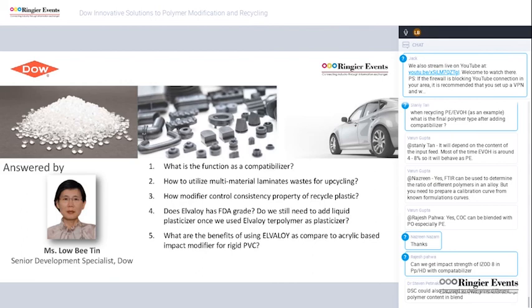The third one is that Elvaloy also acts as a processing aid. We have seen that it enables you to reduce the processing temperature by up to 20 degrees, so you can process at 160. With this lower extrusion temperature, it allows you to reduce the heat stabilizer content in your PVC compound, which in turn reduces the overall system cost.